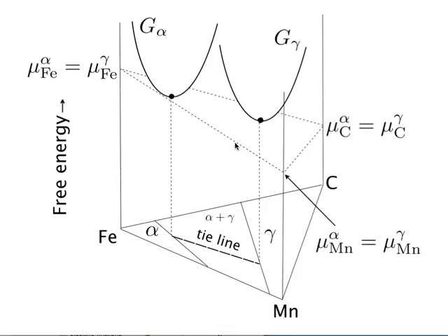And if we now go on to a ternary system, instead of a curve, we've got a free energy surface in three dimensions, and instead of a common tangent, we've got a tangent plane. And because of that, we've got an extra degree of freedom that the tangent plane can rock while still maintaining contact with those two surfaces. So we have a whole set of tie lines, and that defines the alpha plus gamma phase field at a constant temperature, right? In the binary case, you only had one tie line at a constant temperature.